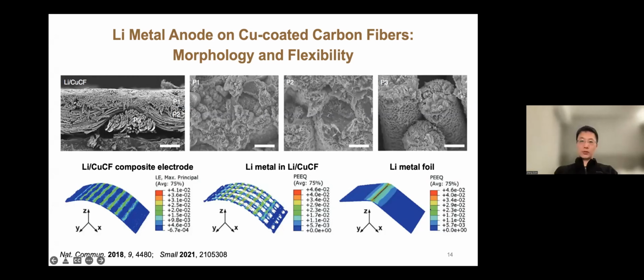If you compare to the one on the very right-hand side, at least the metal one, if you do the same experiment in the simulation, in the same condition, you see there's a huge concentration of force. And once this concentration is there, they will form a crack very easily. And then therefore, the lithium metal will fracture at the end. For the composite one, even though you do have some concentration, they don't actually fracture or crack. We also extracted the data to see what the pure lithium metal looks like. You will see a similar result, that you do have some stress. It's not high enough to induce a fracture. There may be some tiny cracks, but not enough to induce fracture.